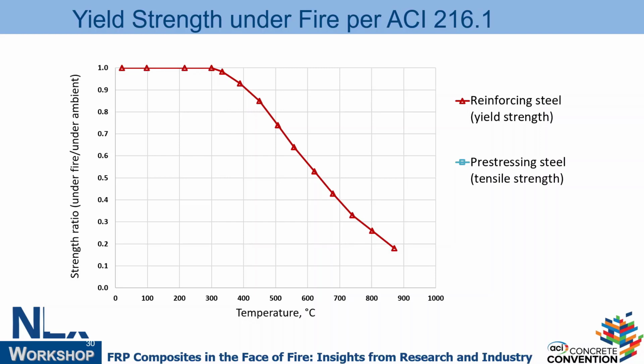But what that tells me is, if I have a tool or a way to determine the temperature of the steel, the bars within my cross-section, I can determine the residual strength after an hour, 2 hours, or 3 hours. And if I know that, I can calculate the capacity after 1 hour, 2 hours, or 3 hours of fire exposure. So this is a very important piece of information. That's why 216 is updating all these curves, because you need these to do what we call rational analysis, rational calculation for fire rating. And if I look at pre-stressing steel, it's a little bit more aggressive. Again, there are many different curves within different codes and research.